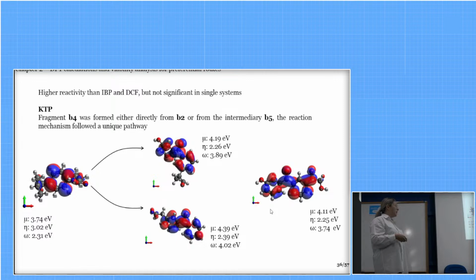For ketoprofen, as a slower fragmentation by the removal of terminal ramifications of the molecule was observed, we saw the possibility of forming fragment B4, this one here, directly to B2 or B5. So here there were no significant variations in the kinetic rate over the reaction.